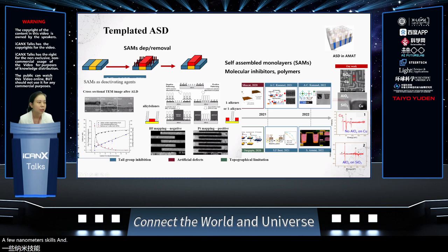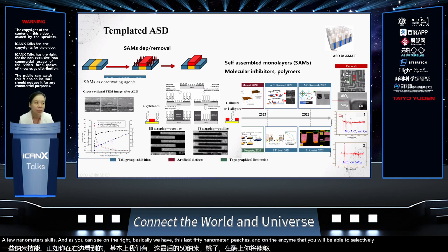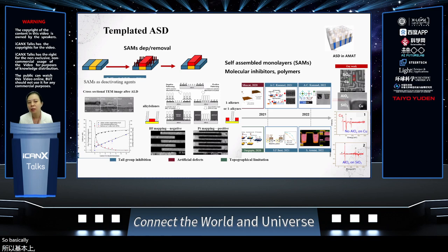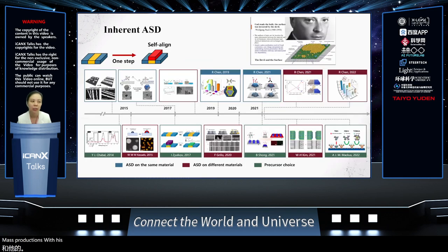And as you can see on the right, basically we have less than 50 nanometer pitches. And on the SiO2, we'll be able to selectively deposit aluminum oxide, while the copper remains completely intact, as shown here. So basically, this is already very close to industrial applications, and I look forward to seeing mass production with this kind of technique.